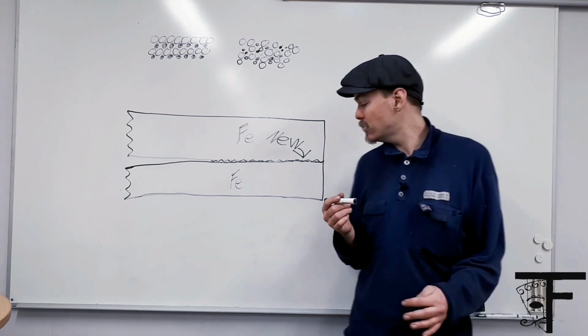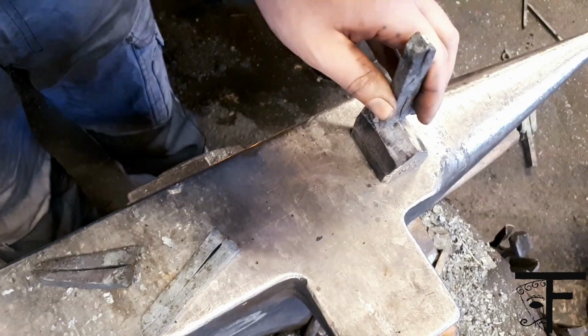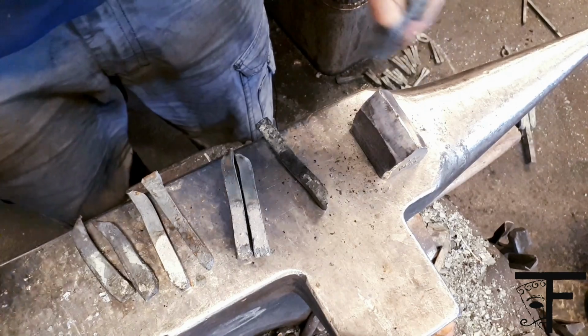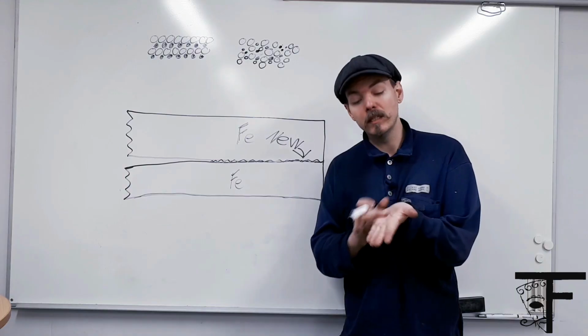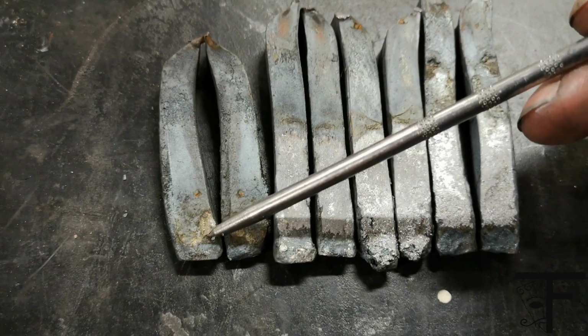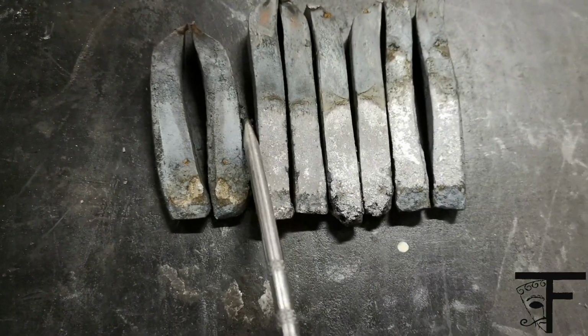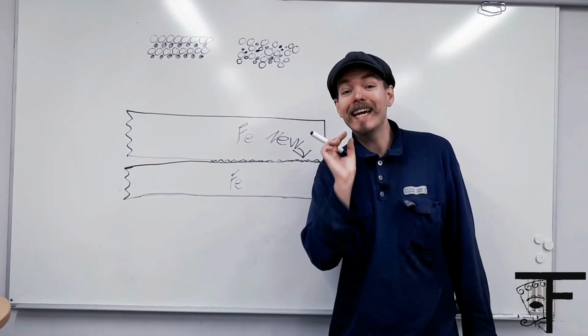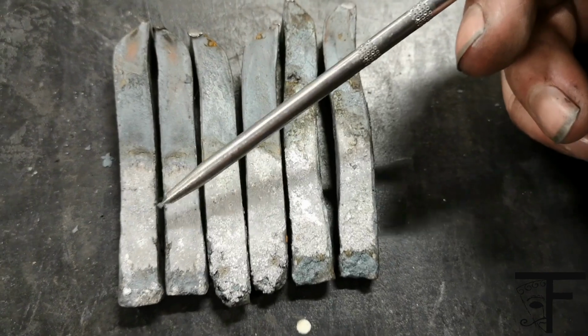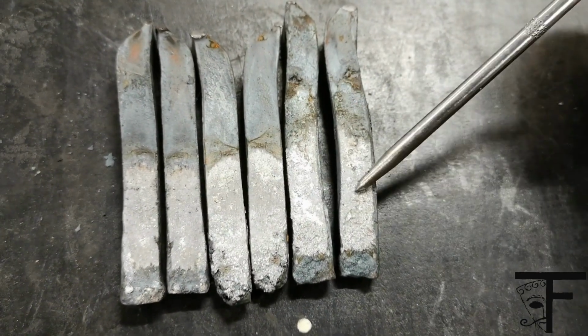Best way to see if it is a good line is to just crack it open and see the crystallization. You see, this one is terrible because it's only been welded on this point, so we take this away. And I want it to be clean. And then we have this one. This is a good weld. This is a very good weld.